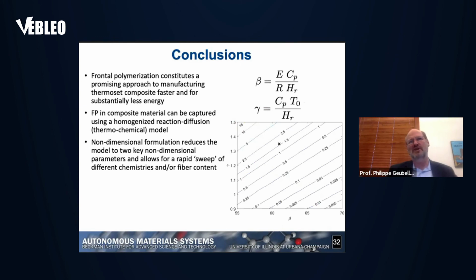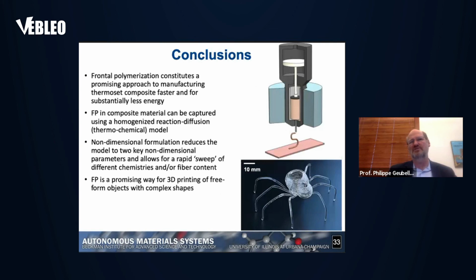To capture the possible deformation of the process. The non-dimensional formulation reduces the model to just two key non-dimensional parameters, and this allows for a rapid sweep of the different chemistries and or fiber content. And then it's also a promising way for the 3D printing of free-form objects with complex shapes.